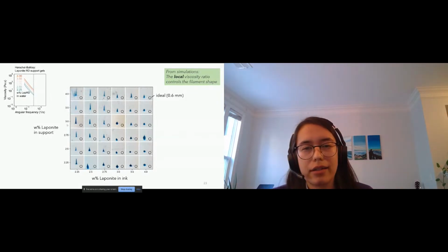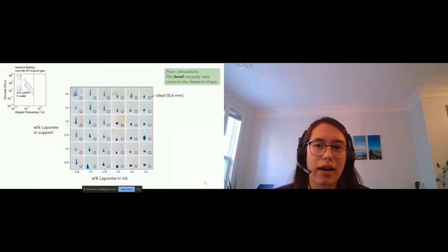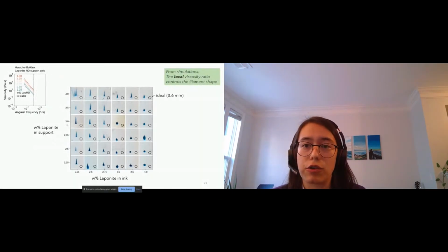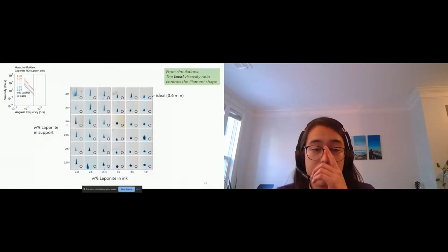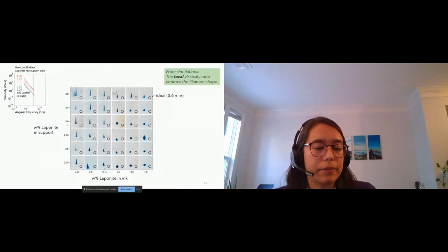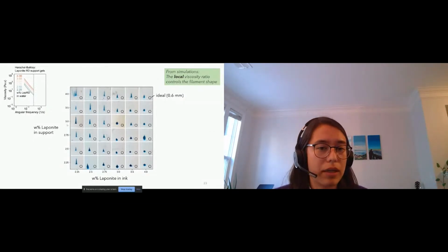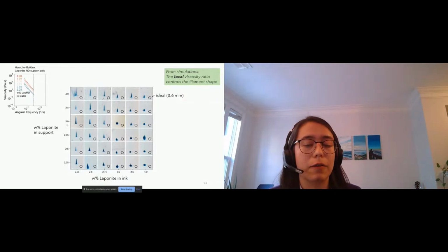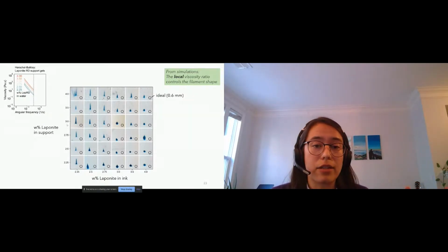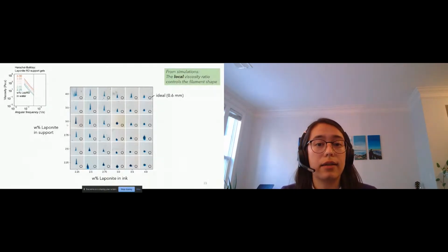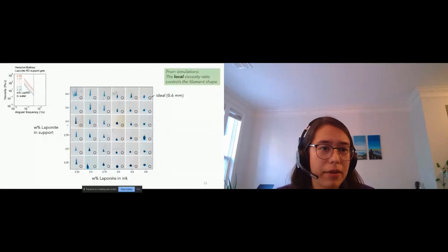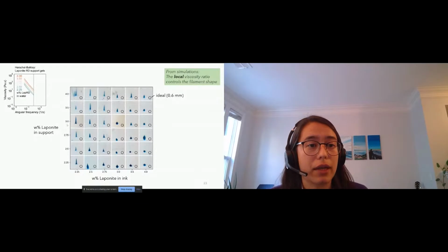So in order to compare this to the simulations, remember the simulations taught us that the local viscosity ratio controls the filament shape. So let's identify the local viscosity ratio. You can get that by taking your print speeds, so the speed of ink moving through the nozzle and the speed of the stage moving underneath the nozzle. Divide that by the dimensions of the nozzle, and that'll give you your shear rate. Plug that in, you can get your local viscosity. So in the top left corner, you can see those dotted lines. Those are our local shear rates. So that's how we get our local viscosity.